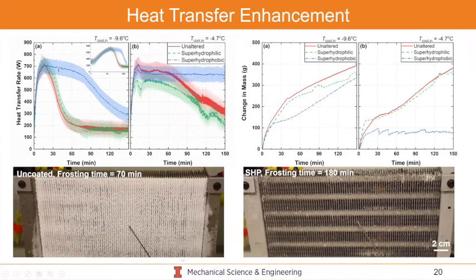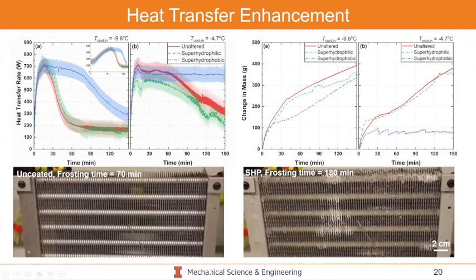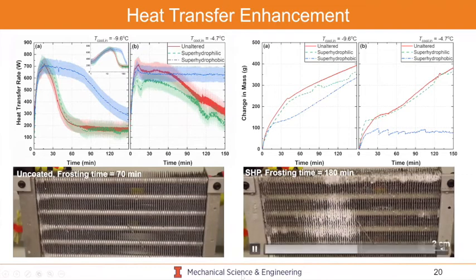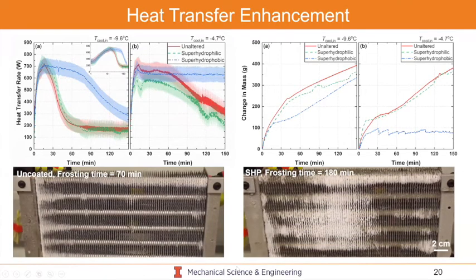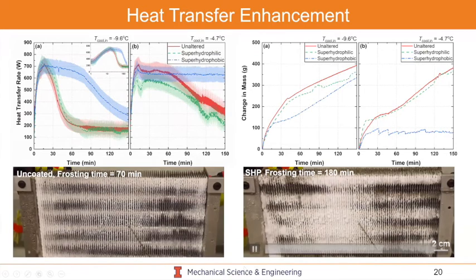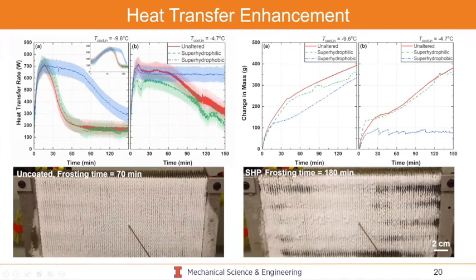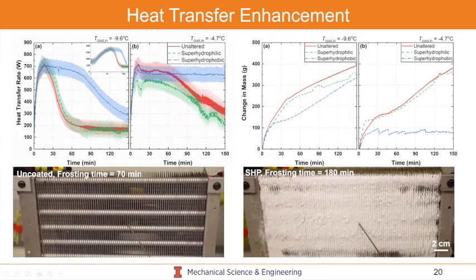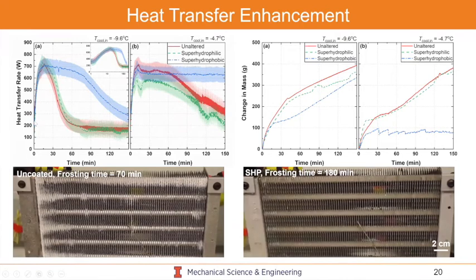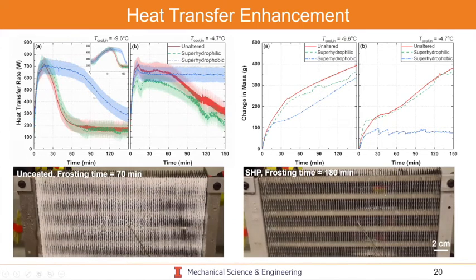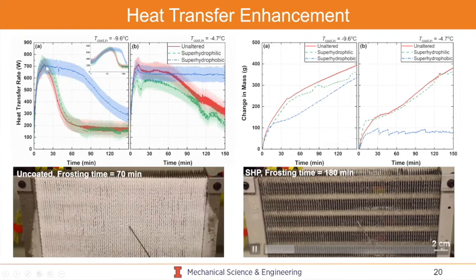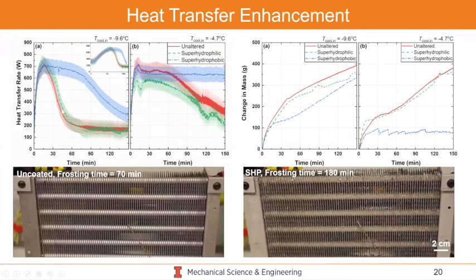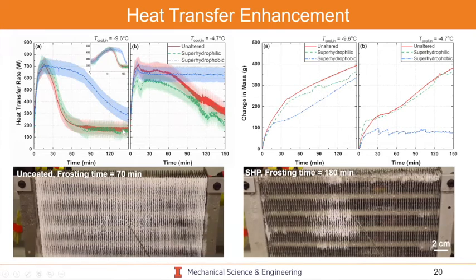The video on the left is actually just the as-is heat exchanger, and the video on the right is a super hydrophobic one. And you can see that there's a significant delay in the frosting behavior on the super hydrophobic one, mainly because you're shedding the liquid very efficiently into the airstream. And so what this equates to is, if you plot the heat transfer rate as a function of time, you maintain a very high heat transfer rate for the heat exchanger on the right here, which is super hydrophobic, but your heat transfer rate on a wetting heat exchanger, or as-is, just decays because the frost grows on the surface, and you have very inefficient thermal pathways from your coolant to your air.